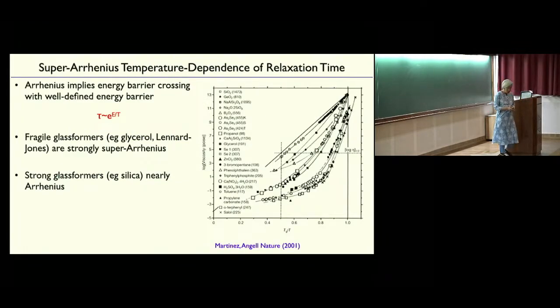So what do I mean by this faster than Boltzmann-like increase of the relaxation time? If you plot the log of the relaxation time, this is log of viscosity, but it's the same thing, versus 1 over temperature, you would expect a straight line if it were just Boltzmann-like. And what you see is that for many liquids, it's not a straight line. It shoots up very, very rapidly. This is the famous Angell plot, named after Austen Angell, who died recently.